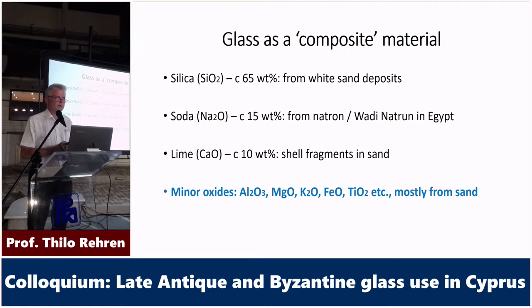All of this glass, it's important actually to see as a composite material, as an additive material. If we just step briefly back, if you look at metal production, you take a very complex ore out of the Troodos Mountains, which has a dozen chemical elements in it, and you make a lot of chemistry to extract just that one element you want, copper, silver, whatever it is. For glass, it's the other way around. You take two or three clean raw materials and you combine them to one final product, which then is chemically pretty complex. And that is helpful, actually, for us.